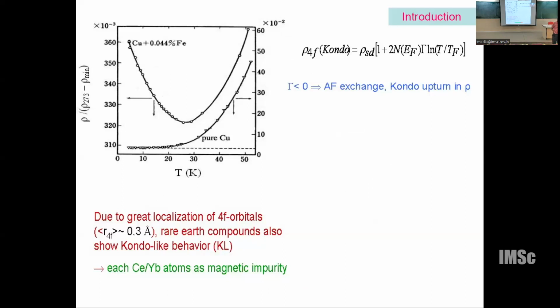Now the question, where is this from? Let me slightly deviate a bit. In the 1950s or 60s, people found, for pure copper metal, this is the electrical resistivity per temperature. You should go like this, taking really pure copper. However, if it contains a small amount of iron impurity, you will find the resistivity goes up. So there's a minimum in the resistivity. This bothered the community for quite some time.